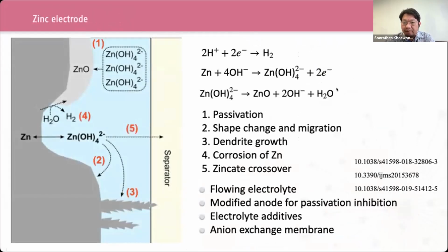However, several barriers impact the practical application of rechargeable ZAPs. Our group has focused on overcoming these issues with different strategies. First, passivation of the zinc electrode with zinc oxide, which is the discharge product, shape change and migration. As the charge-discharge cycle continues, dissolution and deposition of zinc repeatedly occur. Zinc tends to deposit at different locations and in different morphology. This issue affects performance and stability of the batteries.